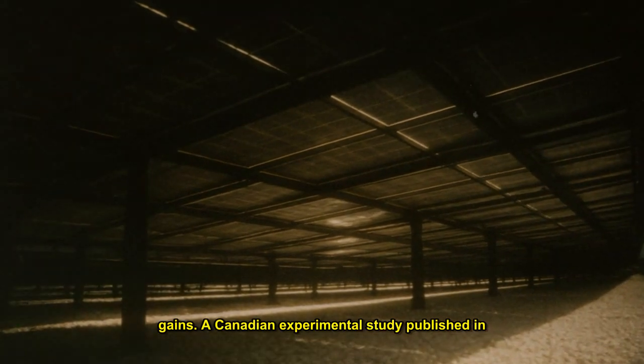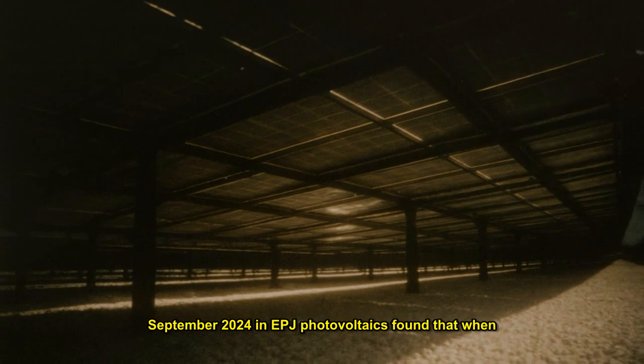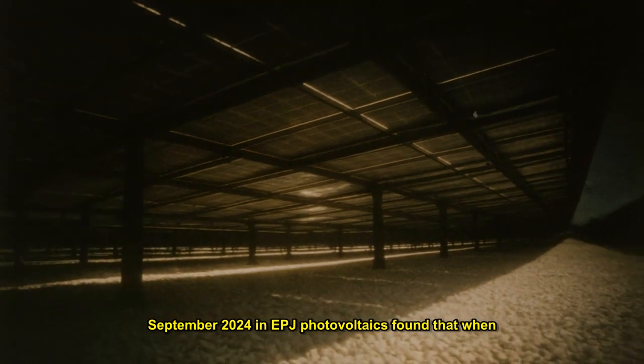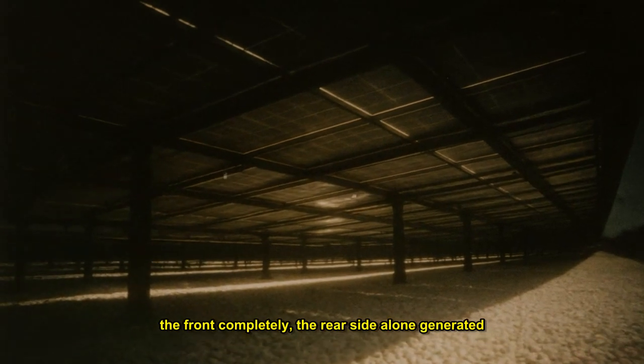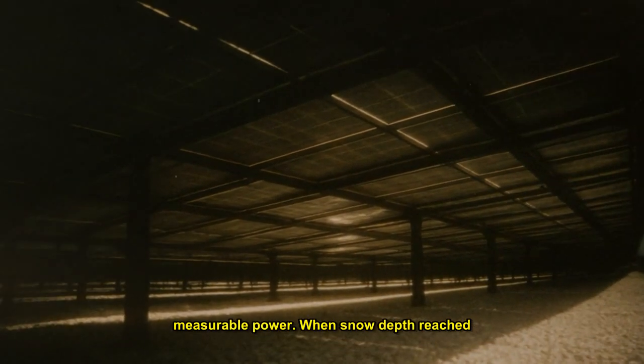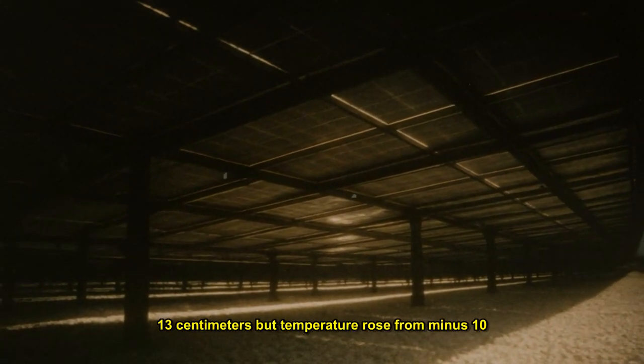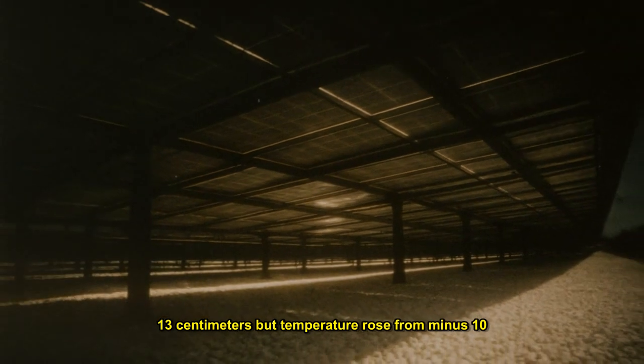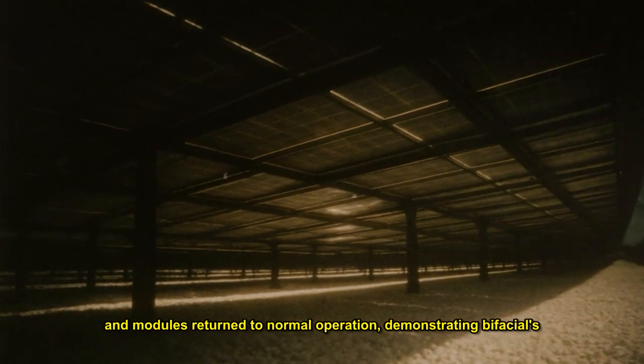A Canadian experimental study published in September 2024 in EPJ Photovoltaics found that when snow accumulated to 2 centimeters and covered the front completely, the rear side alone generated measurable power. When snow depth reached 13 centimeters but temperature rose from -10 to plus 5.5 degrees Celsius, snow slid off the front and modules returned to normal operation, demonstrating bifacials can continue generating in conditions that disable monofacial panels.